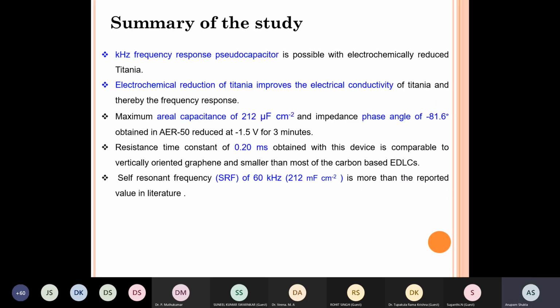So to summarize this study, we showed that it is possible to have a kilohertz frequency response capacitor, and we showed it using titania. Of course, electrochemical reduction of titania improves electrical conductivity is something that I did not include in this talk. The maximum areal capacitance was about 212 microfarads per centimeter square. Compare this with around 30 to 40 for aluminum electrolytic capacitors, which are presently used in all commercial filtering circuits. It's about 6-7 times. So if this was to be used, then the size of the capacitor can go down maybe by 4 or 5 times.